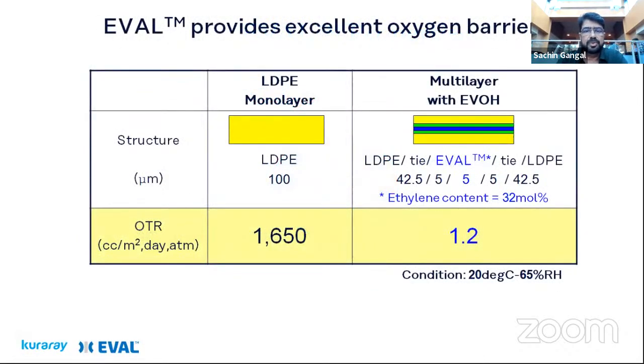So this is just a simple explanation of what happens when you use, let's say, 100 microns of simple LDPE film versus a multi-layer structure. By just incorporating 5 microns of EVOH in a multi-layer structure, you can see the drastic difference in the OTR, which goes from more than 1,000 to almost 1, which is a big achievement for any plastic raw material. Next slide, please.